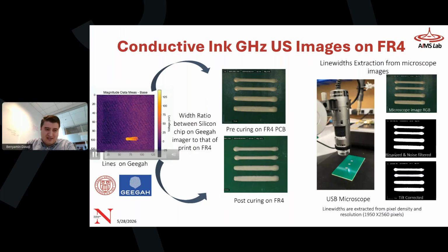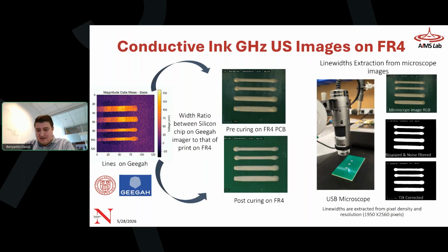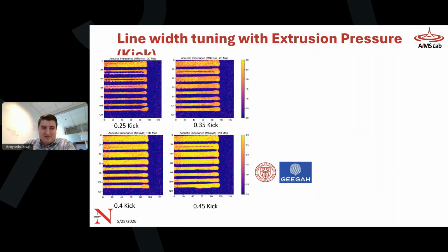Each pixel has a value in voltage, but really shows the amplitude of the ultrasound echo that comes back reflected from the line. And you can also learn the differences between printing on silicon, which this transducer is made of, or printing on FR4, and you can learn the scale factor and correct it. This is work of a postdoc at Cornell, Sai, who has pushed this to be integratable in some sort of a process flow for the Volterra.